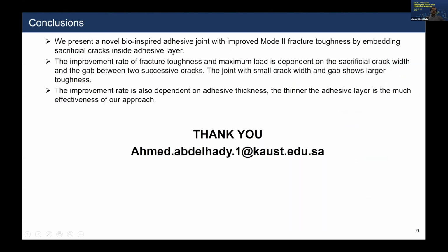So to conclude, we present here a novel bio-inspired adhesive joint. We demonstrate improvement in mode 2 toughness, and in the presentation from Professor Gilles Lubineau yesterday, we demonstrated improvement in mode 1 toughness as well. The improvement rate of the fracture toughness and maximum load is dependent on the sacrificial crack width and the gap between two successive cracks. The joint with small crack and small gap shows larger toughness. The improvement rate is also dependent on the adhesive thickness. The thinner the adhesive layer is, the more effective our approach is. Thank you. I would be glad to answer your questions if you have any.